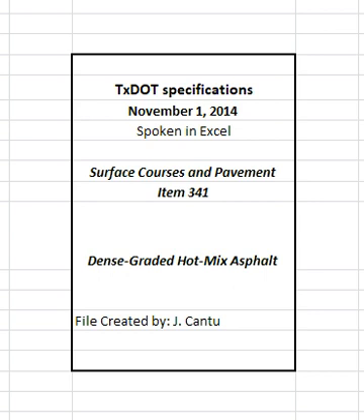4.4.2.2.5 Testing the trial batch. Within one full working day, the engineer will sample and test the trial batch to ensure that the mixture meets the requirements in Table 11. If the contractor requests the option to have the department perform the Hamburg wheel test on the trial batch mixture, the engineer will mold samples in accordance with Tex 242F to verify compliance with the Hamburg wheel test requirement in Table 10. The engineer will have the option to perform the following tests on the trial batch. Tex 226F, to verify that the indirect tensile strength meets the requirement shown in Table 9, and Tex 530C, to retain and use for comparison purposes during production.